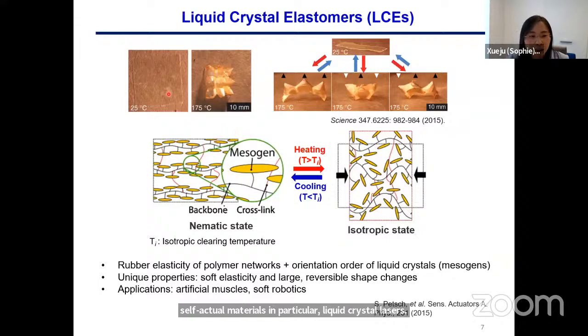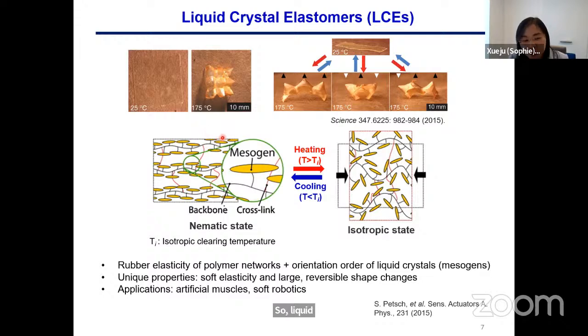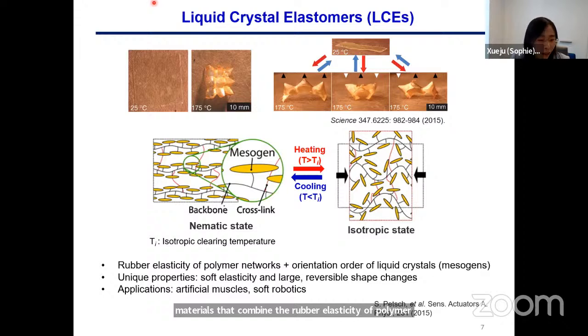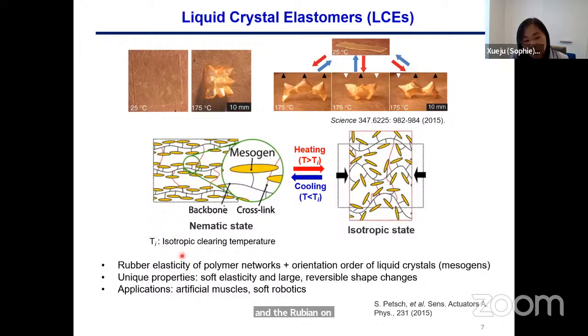Liquid crystal elastomers are a type of smart material that combines the rubber elasticity of polymer networks and the orientational order of liquid crystals. I think we have also had webinars given by Kaushik and Robin on this material. This material has attracted much attention for applications including artificial muscles and soft robotics because of its unique properties, including soft elasticity and large reversible shape changes.